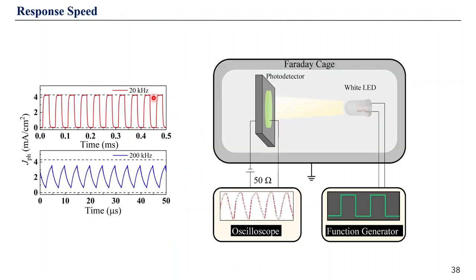It's not enough to have high responsivity and high detectivity. You need to be sure that the photodiode also can respond to fast switching, fast changing light signals. So we use a setup where a fast switching LED is powered by a square wave function generator, and we connect our photodiode via the 50 ohm input channel of an oscilloscope and monitor how the photocurrent is responding to fast changing light signals.